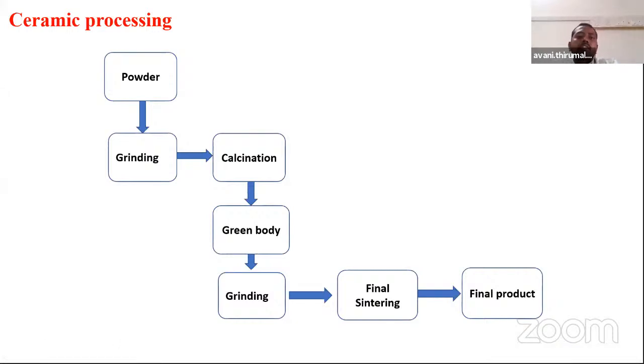This is the normal ceramic processing. First of all, we take the stoichiometric ratios of the powders like zirconium dioxide, titanium dioxide, and lead nitrate as the initial materials. Later, we grind it to reduce the particle size. The properties of the materials depend on the particle size. If the particle size increases, the properties will be different. If the particle size decreases, the properties will change. Depending upon the particle size, all the properties will vary. For that, we are using mechanical ball milling, high energy ball milling.